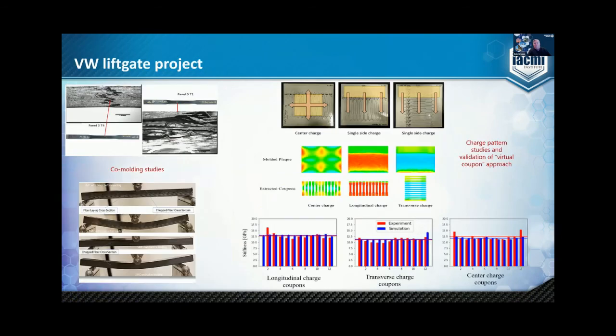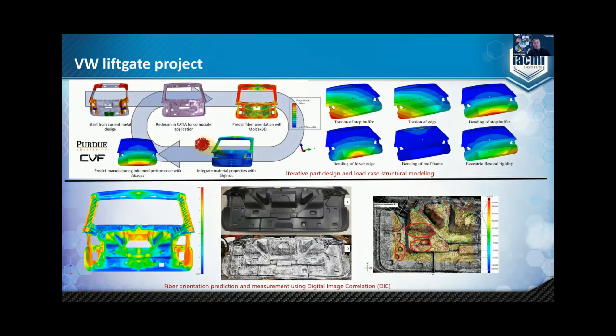On the liftgate project, we initially thought there might need to be some continuous fibers in there, did a lot of work in co-molding studies, but also did virtual coupon approaches to molding SMC, which was surprisingly consistent and very informative. Also on the liftgate project, that had to start with a steel design, went all the way through that, and we wound up with a very lightweight, all composite design that met all the requirements.